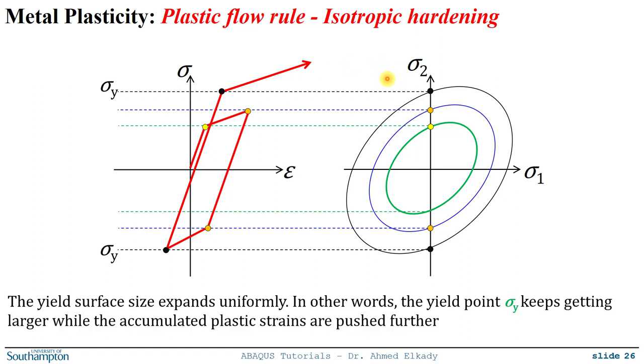on and so on. So basically what you notice here in isotropic hardening is that the yield surface expands uniformly, okay? So it is getting bigger. The center of it doesn't change, all right? So everything is the same. It's only the size of the yield surface that is getting bigger. And in other words, the yield point sigma y keeps getting larger while the accumulated plastic strain is pushed further.